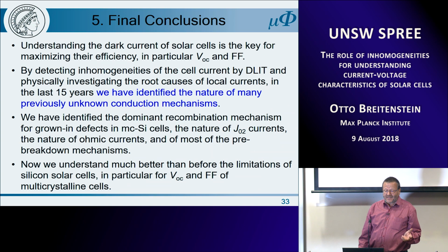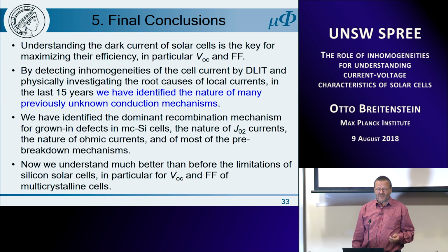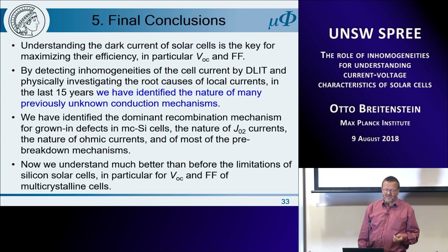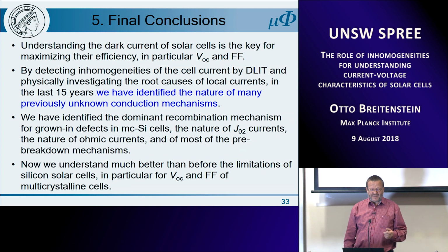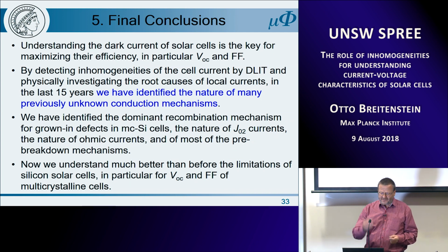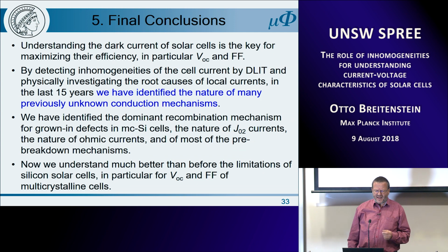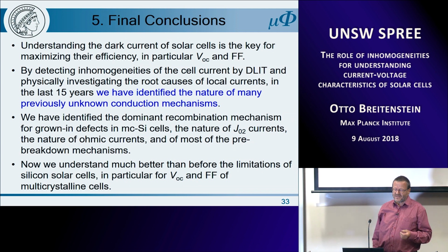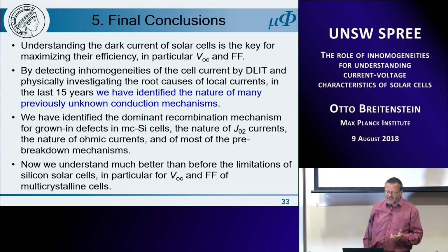And understanding the dark current of solar cells is a key for maximizing their efficiency, in particular open circuit voltages and the fill factor. And by detecting inhomogeneities of the cell current by dark lock-in thermography and physically investigating the root causes of local currents, in the last 15 years we have identified the nature of many previously unknown conduction mechanisms. Namely, we have identified the dominant recombination mechanism for grown-in defects in multicrystalline cells, the nature of J02 currents, the nature of ohmic currents, and of most of the breakdown mechanisms except of this type 1.